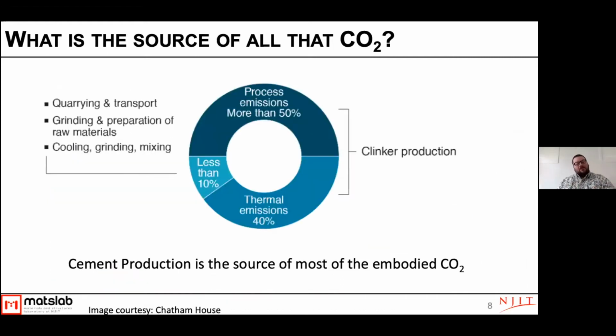And where does it all come from? Well, most of it's coming from the cement. You get some CO2 production from quarrying out the raw materials, grinding it down, preparing it, turning it into a powder. That's really only about 10%. Around 40% comes from what we call the thermal emissions. So this is what is being output from the heating up of the material. We have to heat it up to about 1400 degrees Celsius to get the chemical changes that we need. But over 50% comes from what we call process emissions.